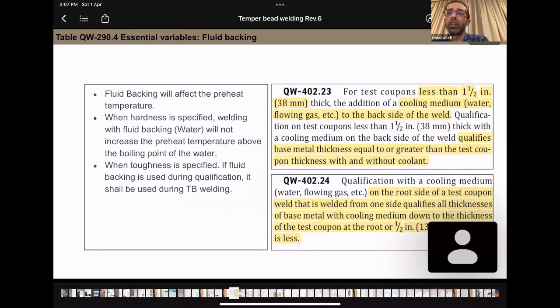And if you refer to QW-290, you will see that there is a limit for the maximum preheat, or increase in the preheat temperature, for the welding method. So the coolant will control the preheat temperature. Like if you have water on the backside, the preheat temperature cannot go above the boiling point of the water. So you are controlling the preheat temperature.